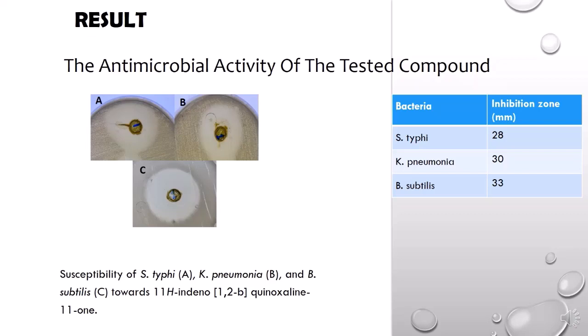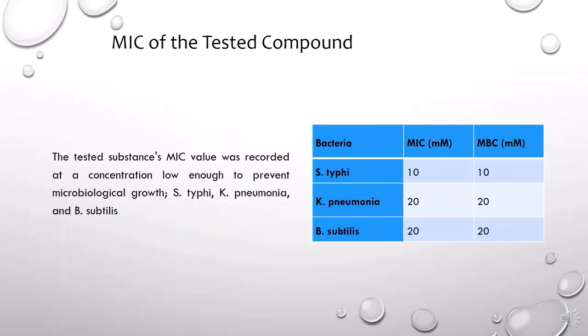The compound has been examined against gram-positive and gram-negative bacteria at a concentration of 20 millimolar by the wells diffusion method, and the inhibition zone was measured and recorded. MIC of the tested compound. We have two definitions, MIC and MBC. MIC is the lowest concentration of antimicrobial that inhibits the visible growth of bacteria, but MBC is the lowest concentration of antibacterial agent that kills a particular bacterium.